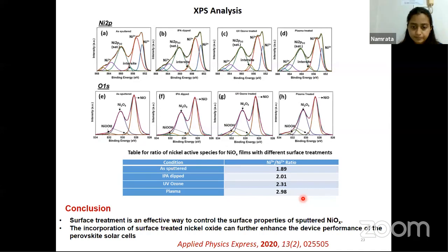device performance. From here, we concluded that the surface treatment is an effective way to control the surface properties of sputtered nickel oxide, and the incorporation of surface treated nickel oxide can further enhance the device performance of the perovskite solar cells.